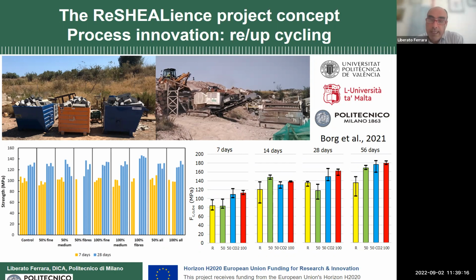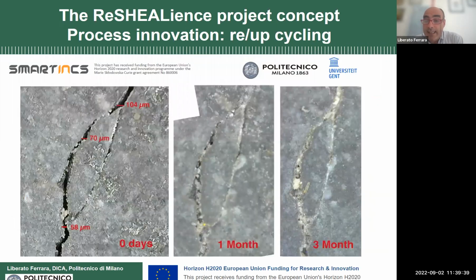And now with the colleagues from University of Malta, we are investigating, with some good results, I would say, the possibility of using these recycled materials also as a partial replacement of the cement, because attached to the grains there are a lot of anhydrated binder particles which can further provide binding capacity. What was interesting in our case is that using recycled UHPC as aggregate, we also kept the self-healing capacity.